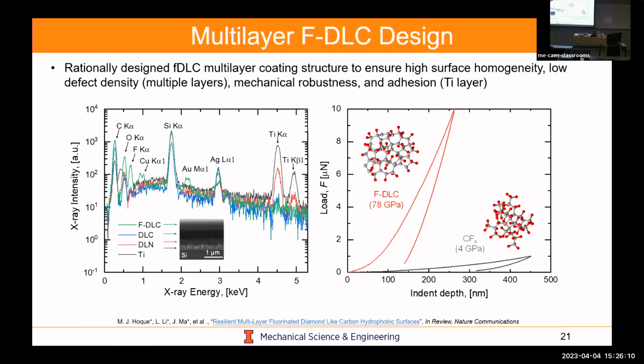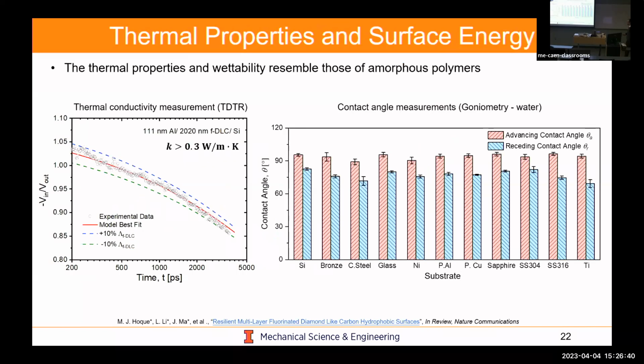The bottom layers essentially give you a gradient in mechanical properties just to relieve stress during deposition. And the multi-layer formulation also acts as a barrier blocker for nucleation or pinhole formation all the way down to the substrate. If you were to look at an indenter load profile as a function of depth, your DLC material is more metal-like than a polymer, right? 4 GPa versus 78 GPa. So very exciting results, and hopefully it works. Hopefully I show you that it works.